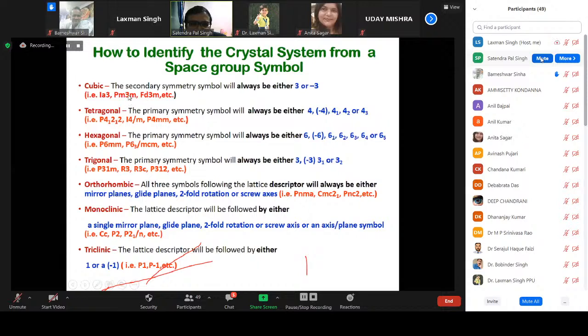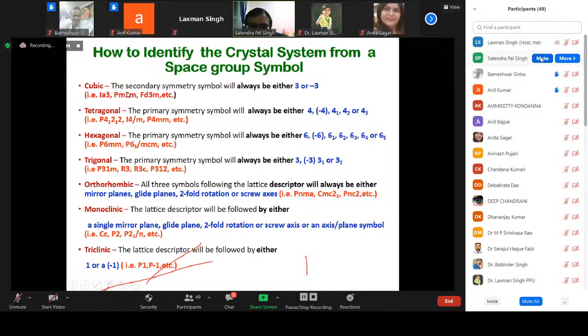So what you have to see is where this 3 is lying. It is lying on the second position. So in the case of cubic, if you see any space group with a 3 at the secondary position, then you say that the structure is cubic. If it is tetragonal, then you will have space groups like P4_12_12 or I4/mmm or P4mm, etc. Then there will be a 4 or -4, 4_1, 4_2 lying on the primary symmetry position, the first position. So the first position is primary, this is secondary, and this is tertiary. So in the cubic system, we will always have a 3 on the secondary position.